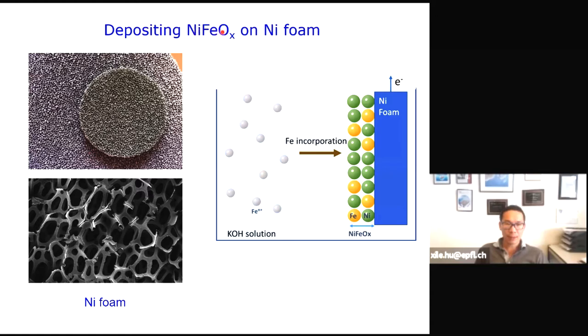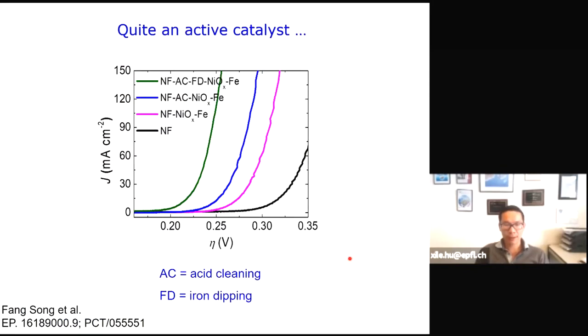A few years back, we were just thinking that if this is the best catalyst, we just want to make a high surface area catalyst, so we decided to put it on nickel foam. We know that if you put nickel foam in hydroxide solution, you oxidize it and will probably make a layer of nickel hydroxide, and under high potentials, it will turn into gamma nickel OOH. We also know from literature that if you have iron ions in solution, they will be incorporated, doped into the structure. So we decided to develop a method useful for making high surface area nickel iron oxyhydroxide on nickel foam. And then we tested its activity and we were surprised.